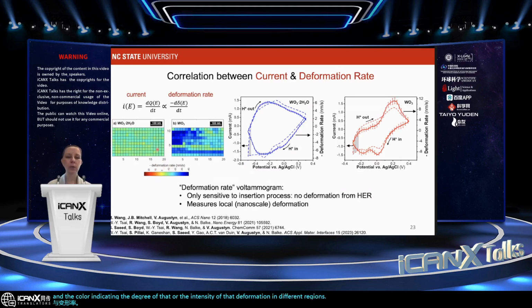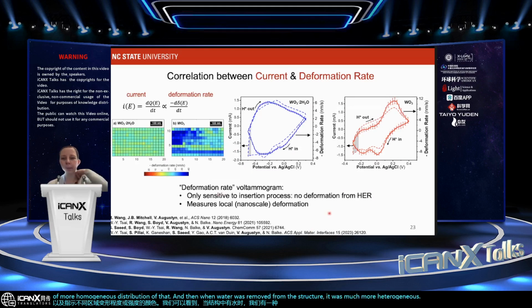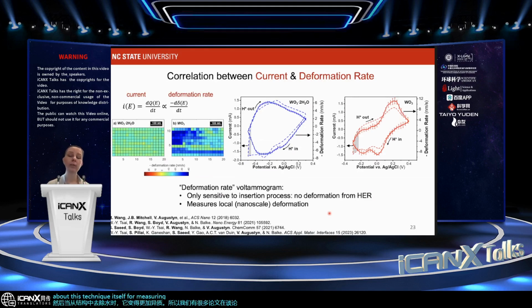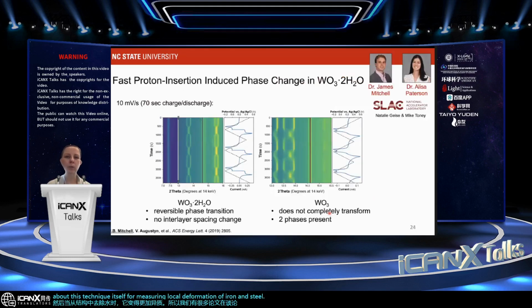And we can see when there was water present in the structure, we had kind of a more homogeneous distribution of that. And then when water was removed from the structure, it was much more heterogeneous. So we have a number of papers talking just about this technique itself for measuring local deformation of ion insertion electrodes.